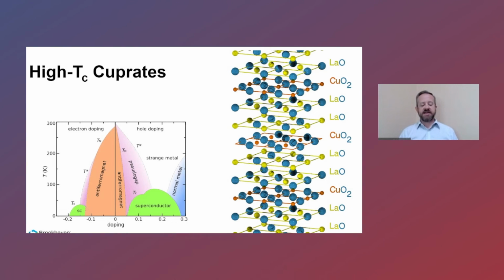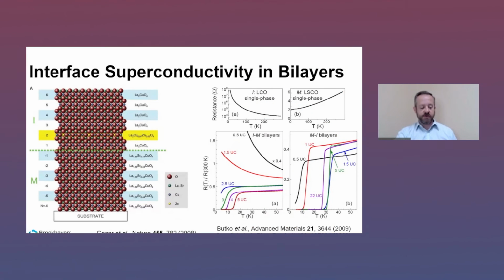But we also like to take advantage of the inherently layered crystal structure of the cuprates, as well as the atomic layer by layer growth mode in our system, to explore more complicated structures than just single phase thin films, such as some early and exhaustive work that the group performed exploring, say, interface superconductivity in cuprate metal-insulator bilayers. I'm not going to really revisit that work here today. The references are here if you're interested. But rather, I wanted to talk about devices with multiple layers. And this is ongoing work.